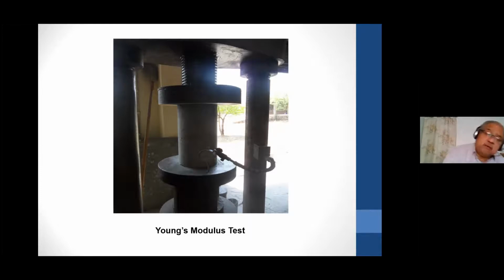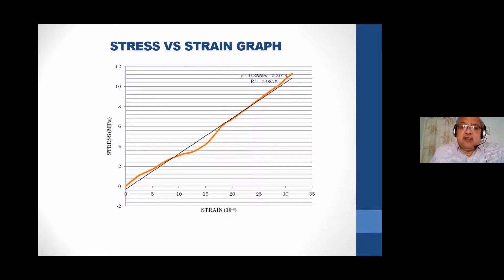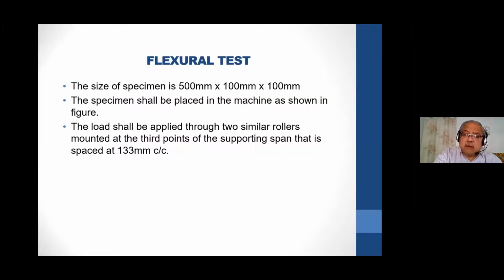We also carried out the load deformation curve for the standard cylinder. This was the picture, and this was the result. Theoretically, it should have been a straight line, but practically we got something shown in orange color. Almost a match. In our conventional concrete, it would have broken at this particular level only, and as compared to this level, see how it has reached higher levels. Hence the modulus of elasticity can very well be ascertained by this test. We also conducted the flexural test.